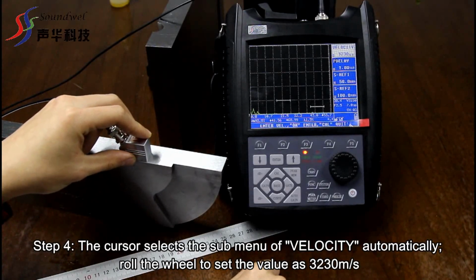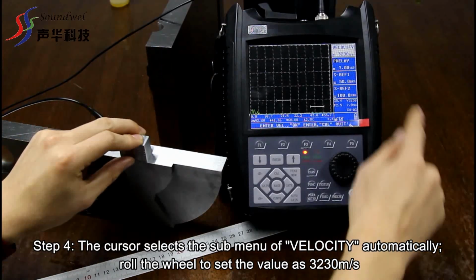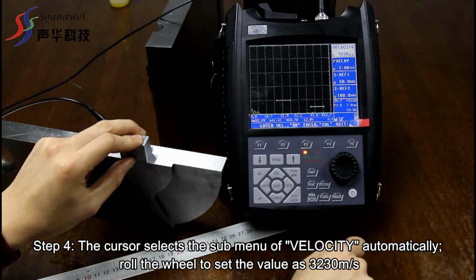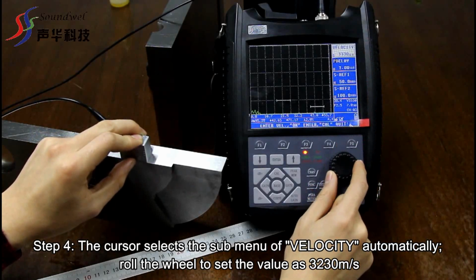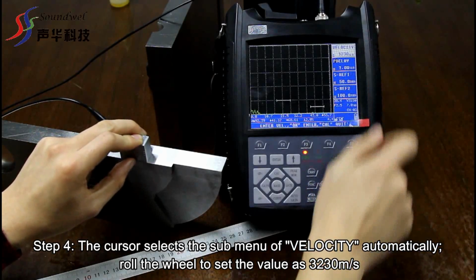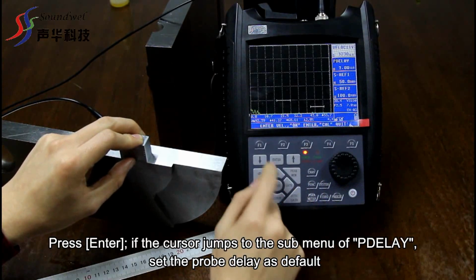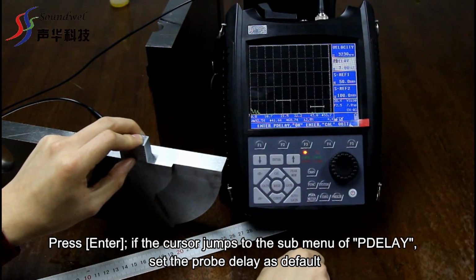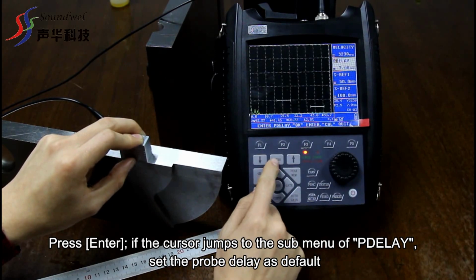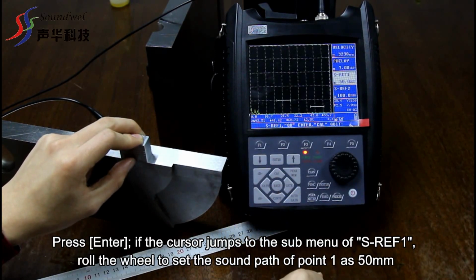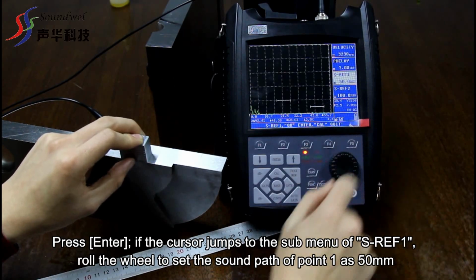Step 4. The cursor selects the submenu of Velocity automatically. Roll the wheel to set the value as 3,230 meters per second. Press Enter if the cursor jumps to the submenu of P-delay. Set the probe delay as default. Press Enter if the cursor jumps to the submenu of SREF1.